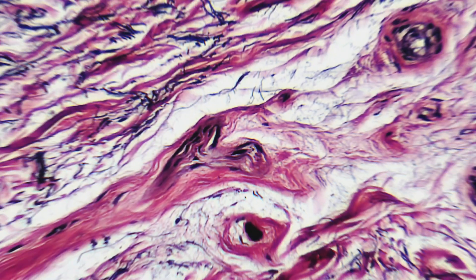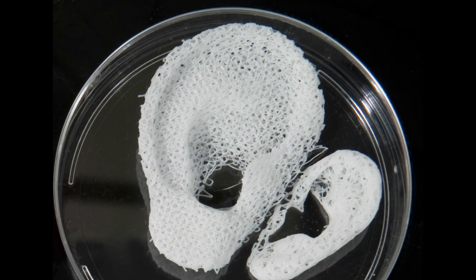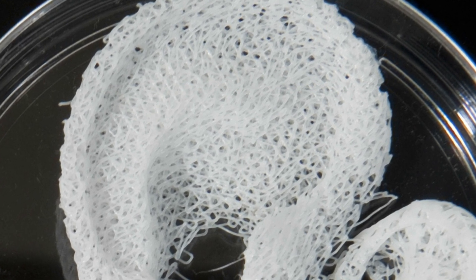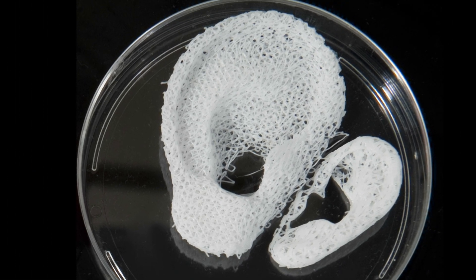The cells heat up when hit by lasers, which can damage them, and it's difficult to construct larger stable tissue constructs with this method. One way to potentially get around this problem is to make clever use of bio-inks. One of the inks can be used as a placeholder that melts away after printing, leaving cavities in the structure. These cavities can then be filled with cells that form a vascular network. This method has been advanced by Dr. Jennifer Lewis and her team at the Wyss Institute at Harvard University to create blood vessels in a 3D printed construct supporting multiple cell types. When printing the ear, a different strategy was used — due to the strength of the supporting bio-ink, the printing could be done quite loosely while still maintaining its ear shape, leaving the ear hollow enough for the flow of nutrients and oxygen to all cells.